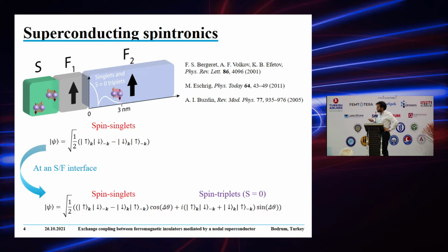I will not go into the details because you heard a lot of talks about this, but you know that when you have a superconductor and a stack of ferromagnets, which you can also consider as a single ferromagnet with a homogeneous magnetization, because of the exchange field at the superconductor ferromagnet interface there is a spin mixing of the spin singlet pairs, and you end up generating a combination of spin singlet pairs and spin zero triplets. Both these components of the Cooper pair wave function decay over a very short distance inside the ferromagnet, because ferromagnetism and superconductivity do not like each other. The exchange field introduces different phase shifts for the two spins inside the spin singlet Cooper pairs of electrons, and this induces a very quick suppression of superconductivity in the ferromagnetic layer.